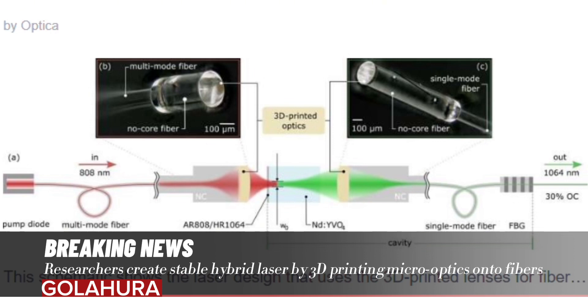Because these 3D-printed elements are made of polymers, it was unclear whether they could withstand the significant amount of heat load and optical power that occurs inside a laser cavity, said Angstenbüger. We found that they are surprisingly stable, and we were not able to observe any kind of damage on the lenses even after several hours of running the laser.